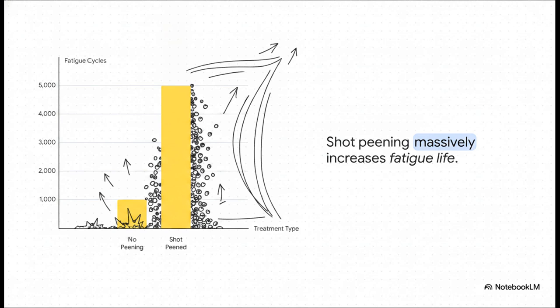When we look at an SN curve, which is just a way to chart the magnitude of stress against the number of cycles a metal can survive, the data speaks for itself. A standard machined part without any peening treatment might survive a few thousand cycles before a crack forms. But by simply shot peening that exact same surface, the fatigue life curve shifts massively upward. The part can suddenly endure exponentially more cycles simply because those initial surface cracks are entirely blocked from ever opening up in the first place.